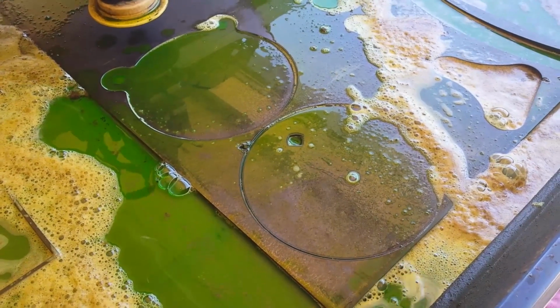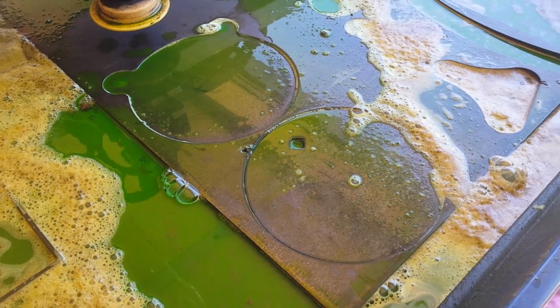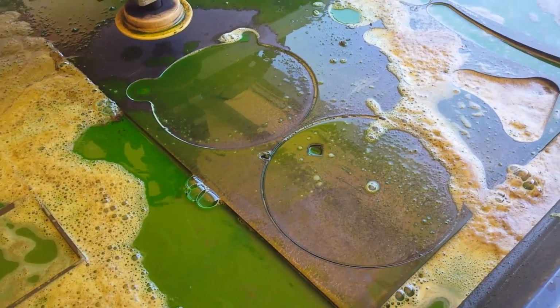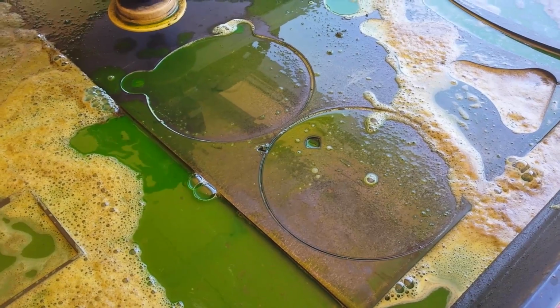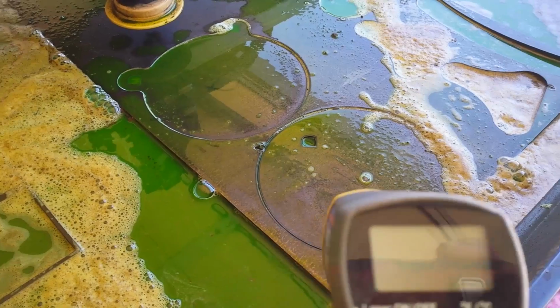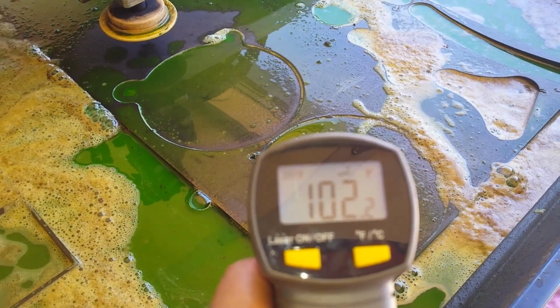Okay, so you can see that I was following the cut, right behind the cut, seconds after, with the laser from this infrared heat detector, and you can see that we hit around 140 during the cutting process, and then it quickly tapered off if I stopped and held a position after the cut. Now we're about 30 seconds after the cut,